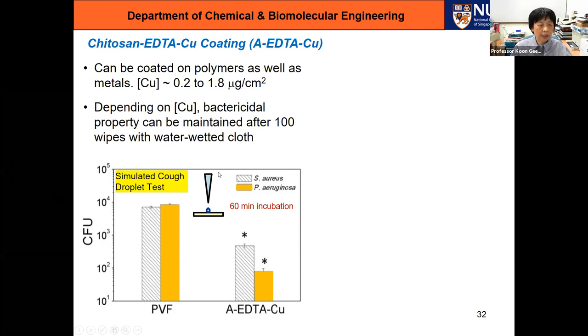So here we are doing a simulated cough droplet test. We put a 1 microliter droplet containing bacteria onto the surface, and we detect how many viable bacteria remain after 60 minutes. PVF is polyvinyl fluoride. We are using that as our substrate because it's very clear. It's a very nice clear plastic. And this is the PVF with our coating. So depending on the type of bacteria, it can reduce by 1 to 2 orders of magnitude.